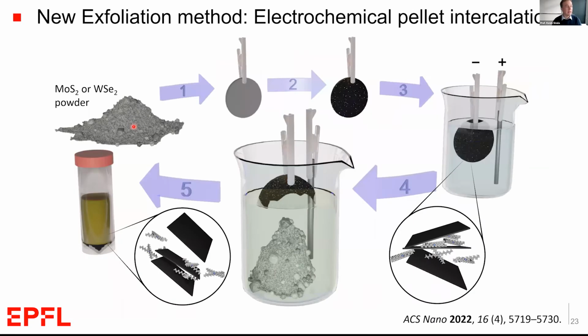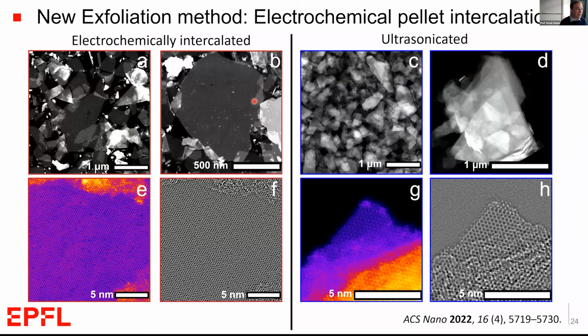Now, most recently, we looked at a new method called electrochemical pellet intercalation, where we take our bulk powder and make it into an electrode where we intercalate a large alkyl ammonium cation, which helps the exfoliation. It's a more gentle type of exfoliation, which means that we can get much larger flakes with more pristine basal planes, as shown here, where we compare TEM images from the electrochemically intercalated flakes to the ultrasonicated flakes.